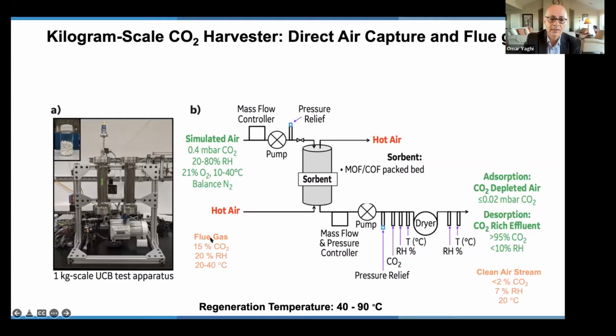With flue gas, let's say coming from burning petroleum, 15% CO2, under these conditions you can cleanse that flue gas down to 2% CO2. What I'm trying to say here is that it's possible to design materials that can extract CO2 from air and that can extract CO2 from flue gas. And now what we need to work on is the long-term stability of these materials. This is a problem that is universal in the CO2 capture world, but I showed you MOFs, and MOFs have a very robust backbone, and these are definitely materials that we are investigating to overcome the long-term cycling stability of these carbon capture systems.